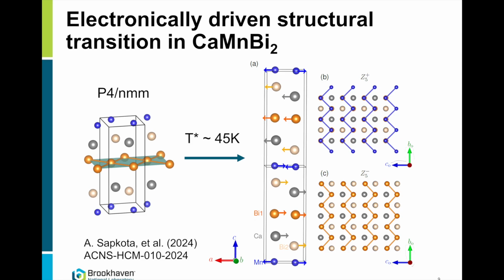or in bismuth layers. However, from the absence of magnetic response at that temperature, but from the presence of resistive response, we inclined in favor of bismuth zigzags. And then, this paper is still being finalized.